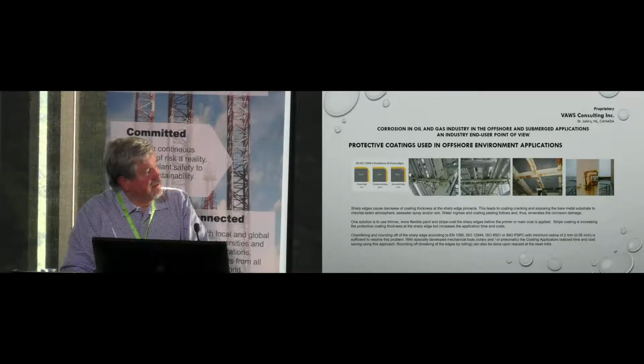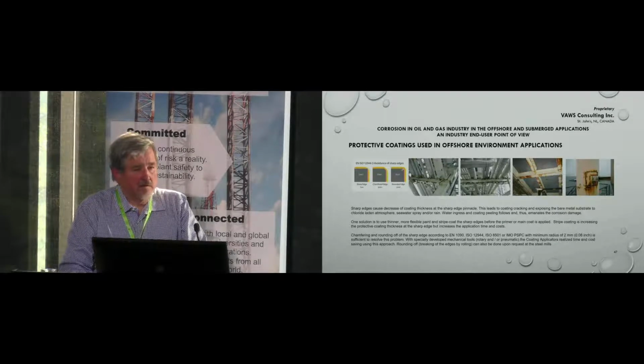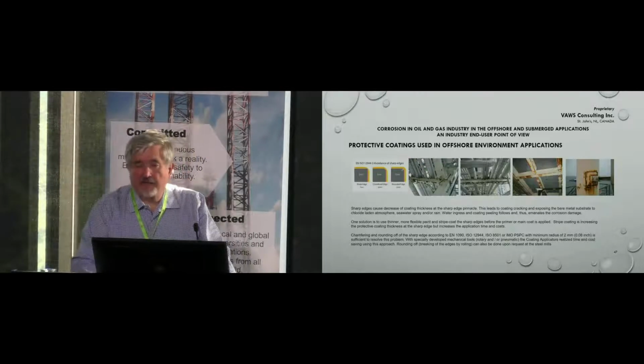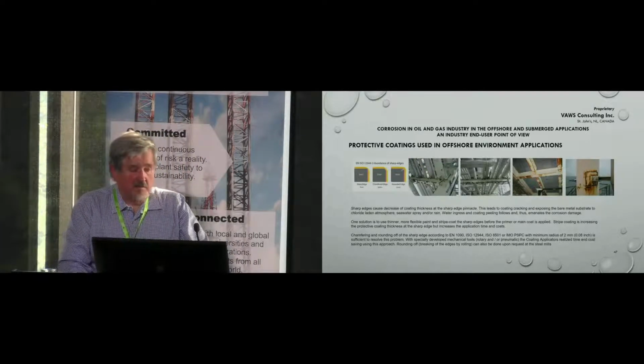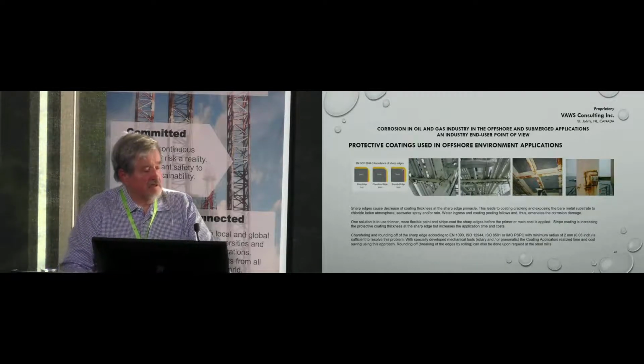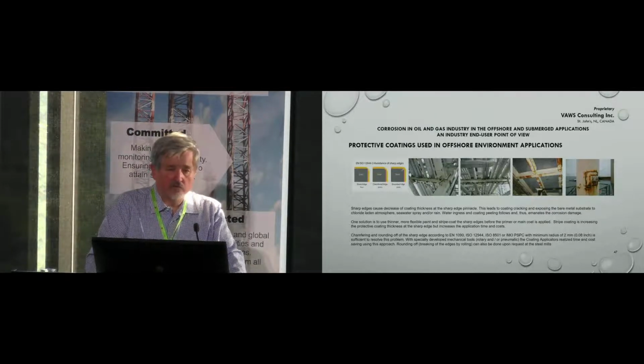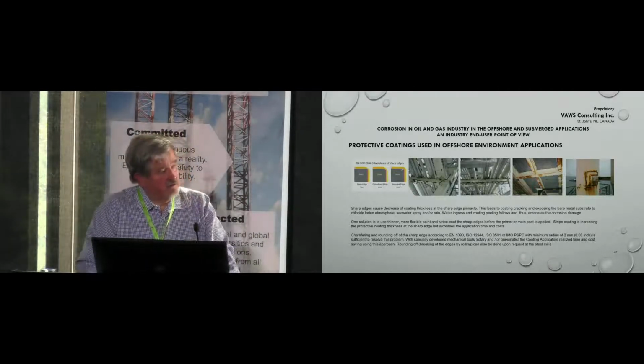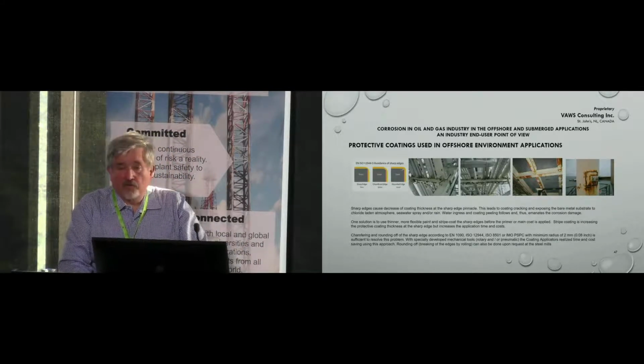We started with rounding up of the edges, and I had great resistance in the shipyards in Halifax. You know, they said it will cost too much money and it will be bad for both of us, company and manufacturer. I said, try it, and recommended some tools. The tool for rounding worked so well that the person who was using it couldn't walk fast enough to keep up with the tool. And I think since then they are using it for everything. There are tools available, and there are cases where the mills themselves round the edges, and what you need is a minimum of 2 millimeters. 5 millimeters is perfect. There are very few paints which will fail on 5 millimeter rounding. And it's the I-beams and these kinds of things which are very difficult to paint to start with. So if you have round edges, it's a good thing for success.